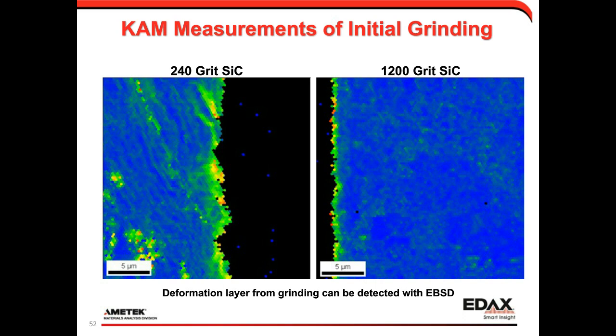Again, this time it's flipped, so the polished side is on the left-hand side of that image on the right. And we see the layer on the same scale at 1200 grit is now much smaller and localized at the surface after those additional grinding steps. So this is kind of just a neat picture to show how EBSD can measure the damage caused by polishing, and also just to give an example of how EBSD can measure that plastic deformation.